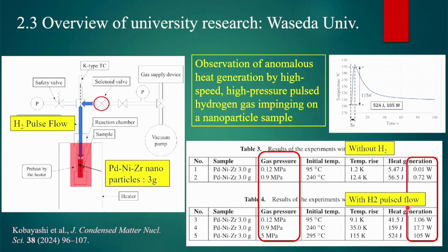So this is the data of the result. Without hydrogen gas, there is very little excess heat, but if they use hydrogen gas, pulsed flow, shock wave, they got very large excess heat, more than 100 watts detected.